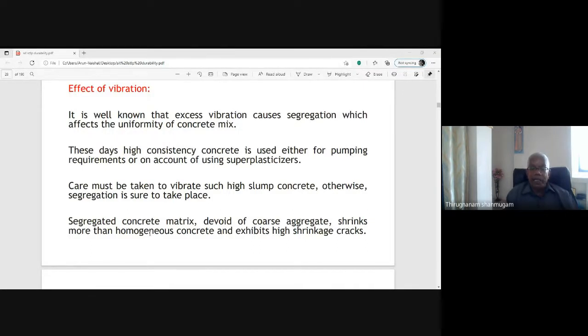Care must be taken to vibrate such high slump concrete, otherwise segregation is sure to take place. This is a flowable or liquid concrete, so the fine aggregate and coarse aggregate can easily segregate from the cement paste. Only very small vibration is needed, or alternatively no vibration, as in self-compacting concrete, SCC. You have to go for self-compacting concrete to avoid segregation. Segregated concrete matrix devoid of coarse aggregate shrinks more than homogeneous concrete and exhibits high shrinkage cracks.